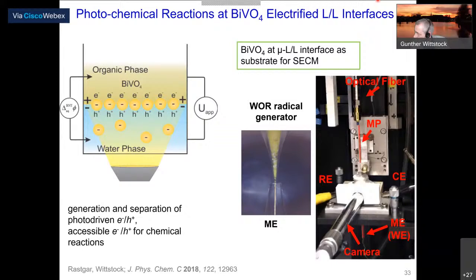Now, does the shape of the electrode impact the adsorbate and subsequent chemical oxidation, electron injection in the cavity microelectrode? Okay, we have worked with gold disc electrodes and produced cavities of different depth. And it seems that we see the same voltammograms regardless of the depth. So there's a very well conducting network of the nanoporous gold, and we don't see any effect of that. We usually characterize that and normalize it either to a current which we get from capacitive current or by a surface gold reduction peak. Again, for that we get very reproducible data, and that doesn't seem to be a problem.